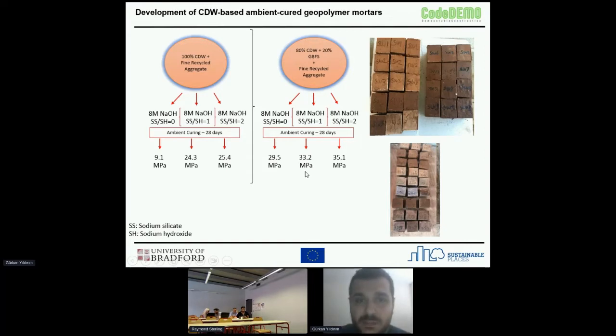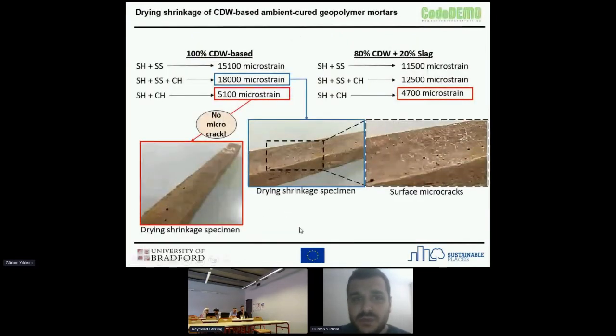But the CoDeDEMO project proposed completely CDW based concrete. So although this strength level is higher in the case of slag usage, we are still trying to develop this 25 MPa strength level, which is fine, but we are still trying to increase the level of compressive strength by changing the mixture proportions and working on different proportions of alkaline activators. So we did some further tests.